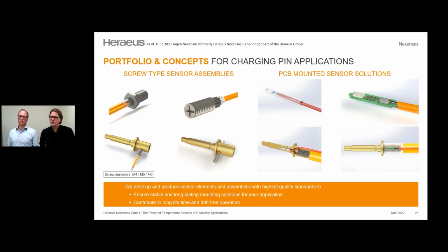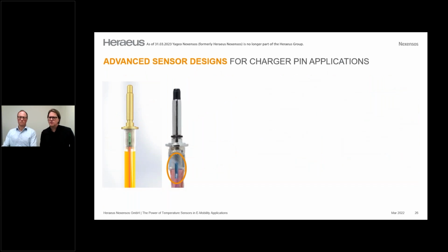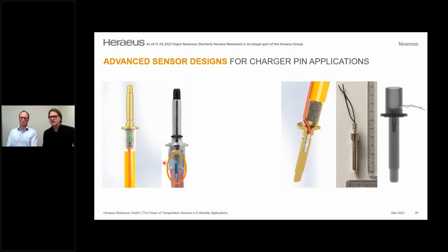We can also use, in the middle part of that slide, again a kind of an EC3032, maybe in a different dimension, to put it directly in a hole in the core of the pin, which enables us to measure the temperature exactly where the heat is generated. And on the right side, you see what we call a PCB version, which is directly mounted on the backside of a pin with a heat shrink tube. In the next slide, you see that this is not only an idea. You see directly the PCB type, which is mounted with a shrinking tube around that metallized back part of the pin, and you can directly measure the temperature.